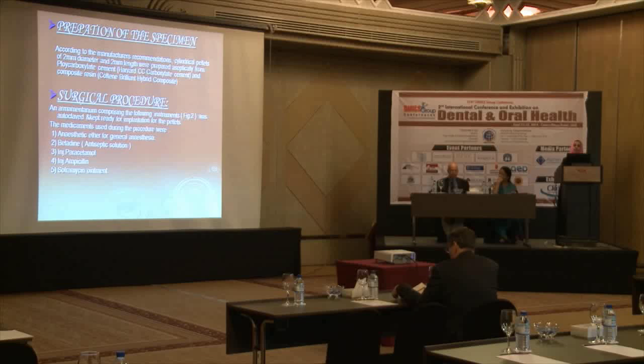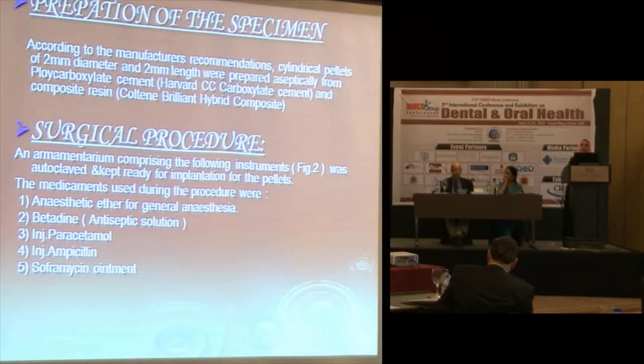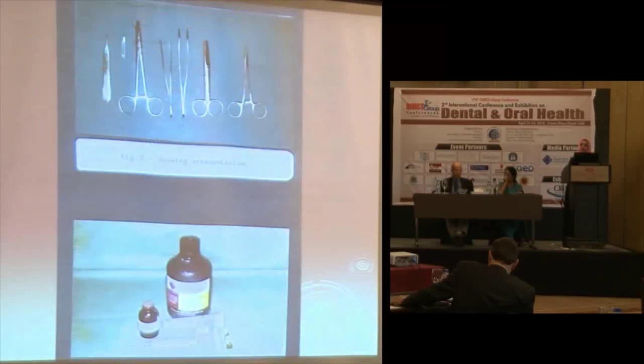Then the preparation: according to the manufacturer's recommendation, cylindrical pellets of 2 mm diameter and 2 mm length were prepared aseptically from polycarboxylate cement and composite resin. The surgical procedure: an armamentarium was autoclaved and kept ready for implantation of the pellets. The medicaments used were anesthetic ether, Betadine, injection paracetamol, injection ampicillin and Soframycin ointment.